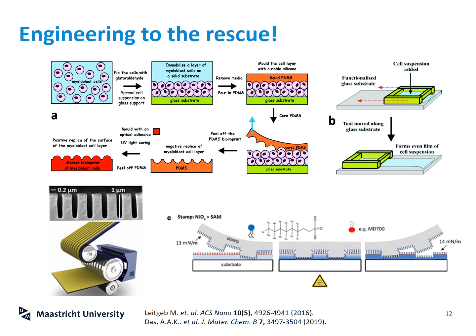Now, you can deposit these imprinted sheets of MIPs onto substrates and you can cut them into pieces. That is where you can use micro-contact imprinting for creating MIPs on a large scale. So this is a very clever way of doing so. The only drawback here is that you lose functionality, right? Normally you imprint the cell, so you have all the carbohydrates, the proteins on the surface of the cells. You will lose some by making a negative master first and then a positive master. So you will lose a lot of functionality. So we'll be a little less specific. Nevertheless, a very cool idea that will get us one step closer to industrialization.